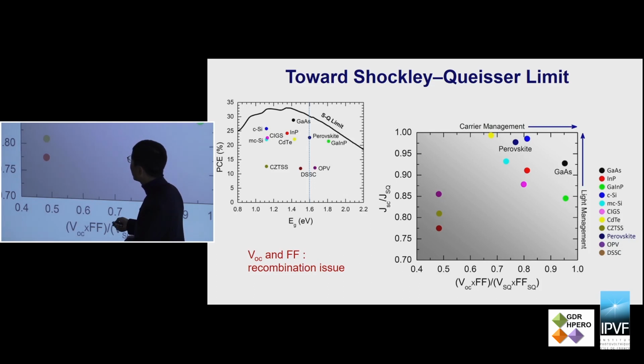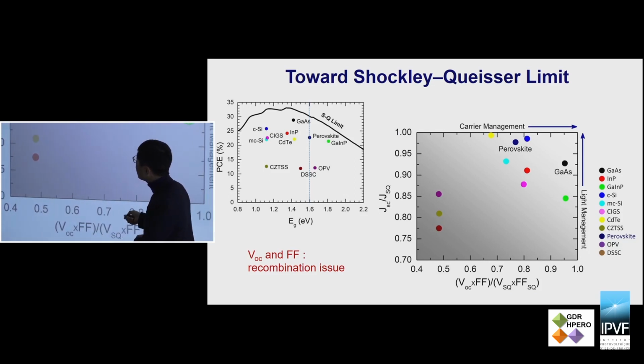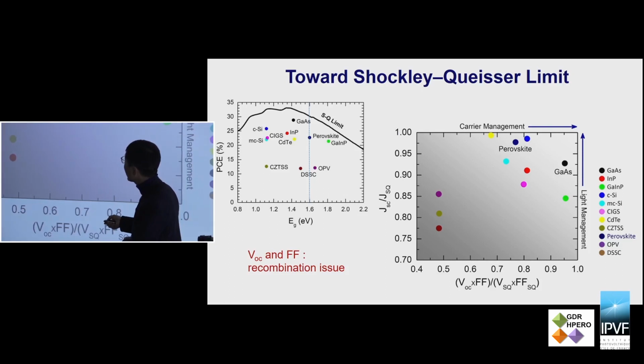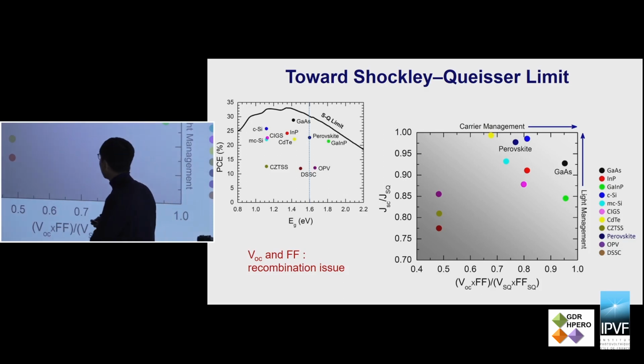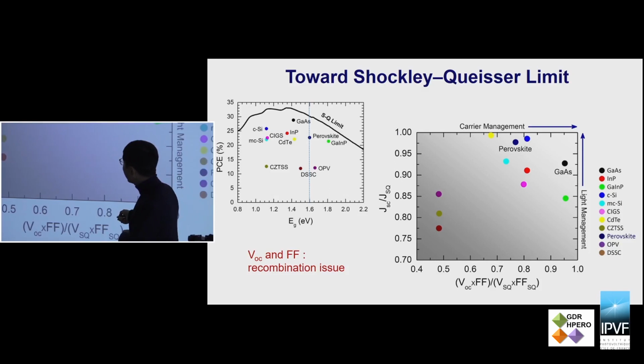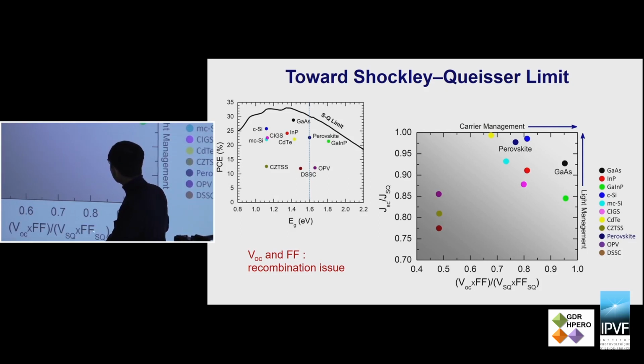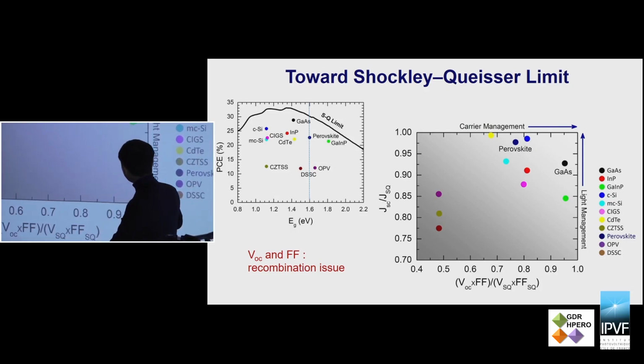Around here we have a 24% efficiency from previous data, and now we have something like 25% here. If you break it down, PCE, power conversion efficiency, is the product of the short circuit current, open circuit voltage and fill factor. If you plot these against the theoretical values, for gallium arsenide the open circuit voltage and fill factor are very close to the theoretical value. However, there is some gap between the theoretical efficiency and the short circuit photocurrent density.